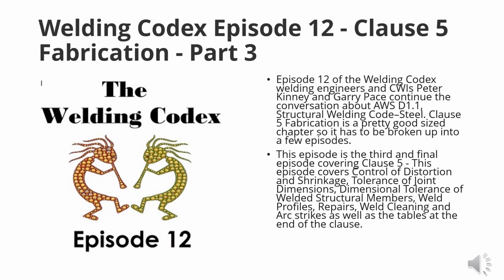So that's just basically telling you if there's something that needs to be fixed, then you have to chip it out of there, chew it out of there, remove it by whatever method is acceptable to your contract and/or engineer or your company's quality plan, and then you clean it up and put it back in there, and you try to remove as little of the base metal as possible. Correct. And this thing about the oxygen gouging is hot, really hot. It's fast. It's super fast because it's so hot. And when you have any material besides as-rolled steels, the heat can start to affect things, and that's kind of the basis for this limitation here. So there is a rationale for it, which I can stomach.